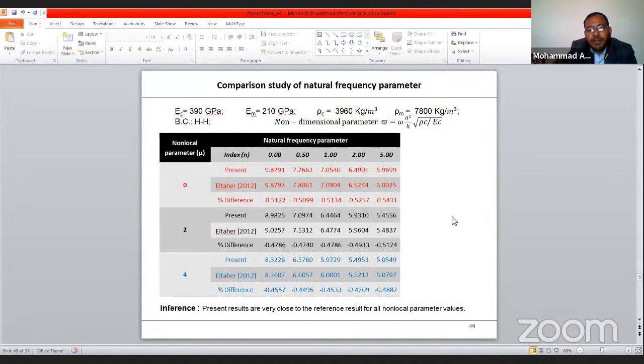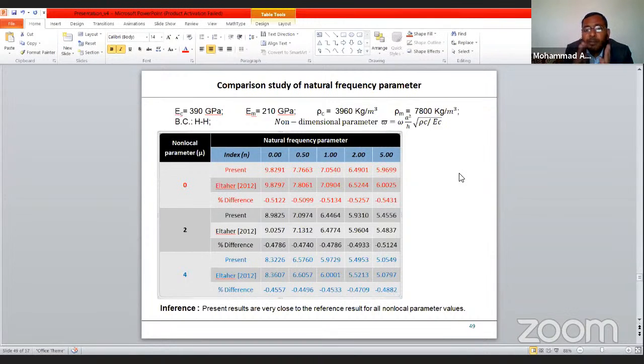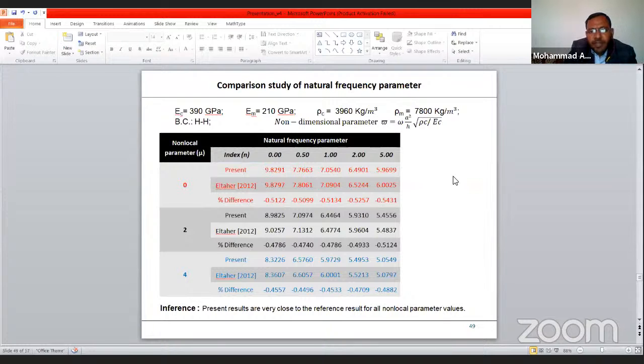This is another comparison where we have considered non-local parameters 0, 2, and 4, and the effective material properties are given here, and there I have considered hinged boundary condition, and the results are presented for various values of the volume fraction index. This volume fraction index n governs the composition of the ceramic and metal. For n equal to 0, it's 100% ceramic and metal component is almost 0, and for n equal to 1, it's 50% ceramic and 50% metal. So we found that for various values of the volume fraction index as well as various values of the non-local parameters, my results are very comparable with the reference result.